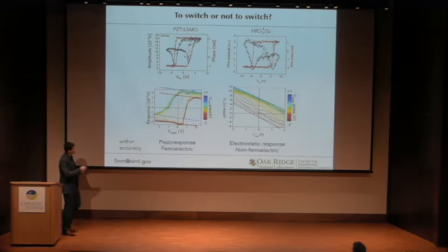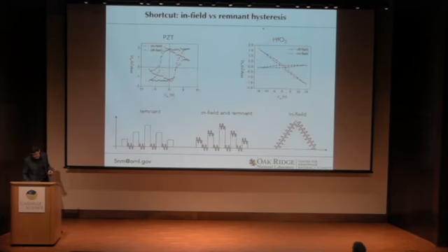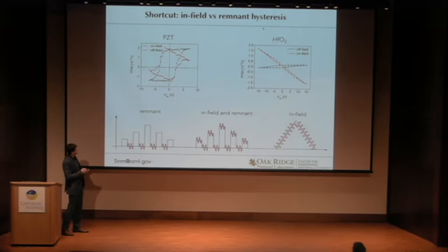So this is dominated by piezoelectric hysteresis, which is not strongly dependent on the read condition, where in this case it's basic electrostatics response, and there's no ferroelectricity to be had within the measured accuracy. And there's actually a shortcut to doing this procedure. Just comparing sort of remnant hysteresis response to what you would get, which is what we call in-field response.